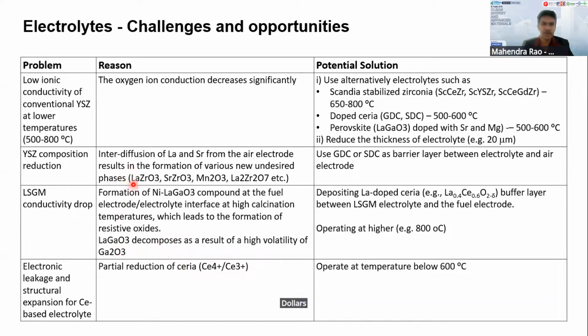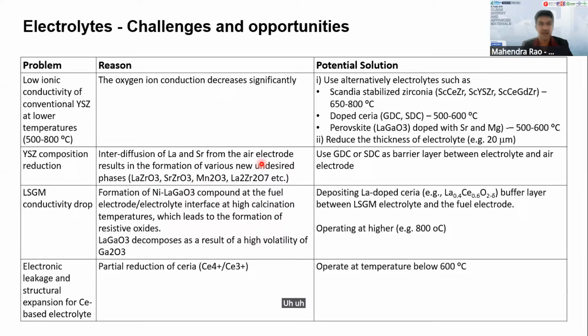And then we know there is some diffusion of lanthanum and strontium from the electrode, resulting in the formation of secondary phases such as lanthanum zirconate, strontium zirconate, and manganese oxide, and lanthanum zirconate. So these are diffusion issues that we face when we use the YSZ with an air electrode. So some of the solutions are very readily available, such as the barrier layers, to reduce these interactions for the YSZ materials.